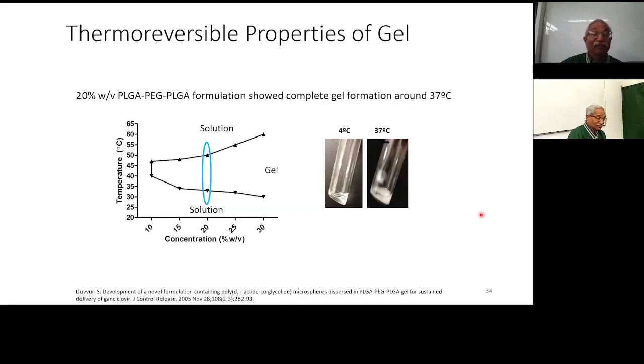So to understand what sol-gel thermoreversible property is, this is your polymer you incorporate into the water or aqueous system, and then it is in solution. At one point it is in solution at 20 degrees, and as soon as it goes to body temperature, 37 degrees, it gets converted into gel. So you have a clear solution you inject inside the eye, and at body temperature it will become a milky gel. When you inject in the rat eye, it's not even one drop. It's a very small dose. So this is how sol-gel formation looks. And it is reversible: if you bring it back to 20 degrees, it will become solution.